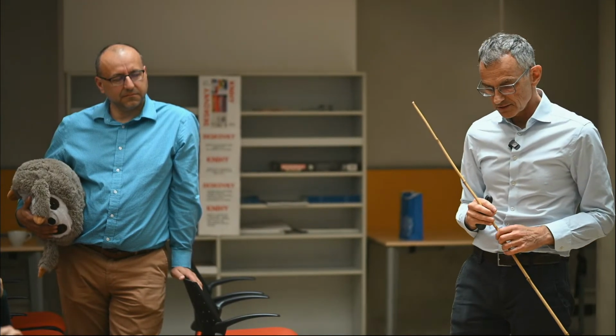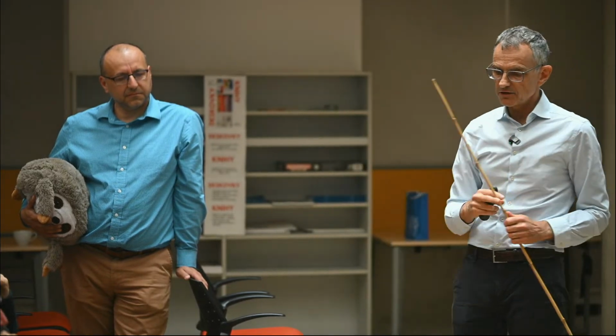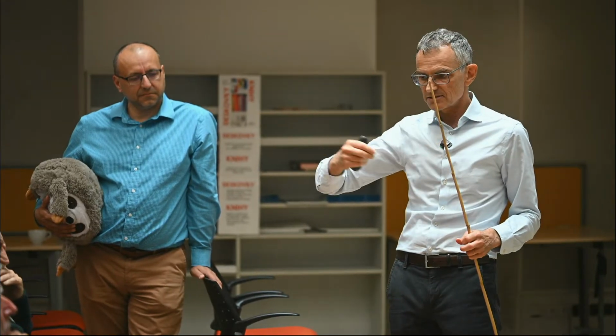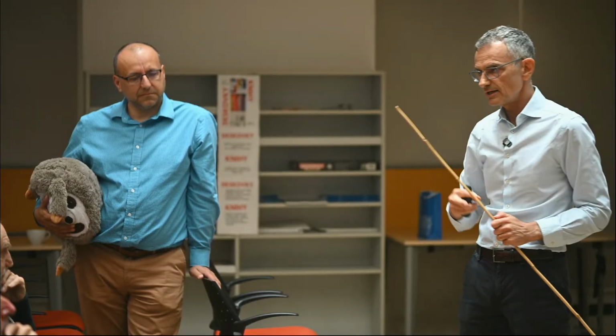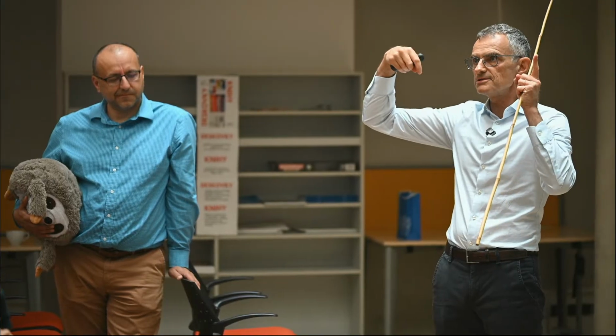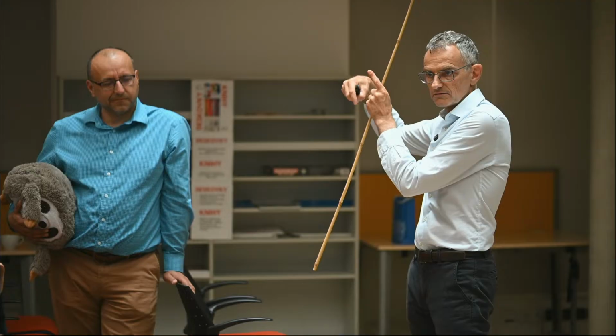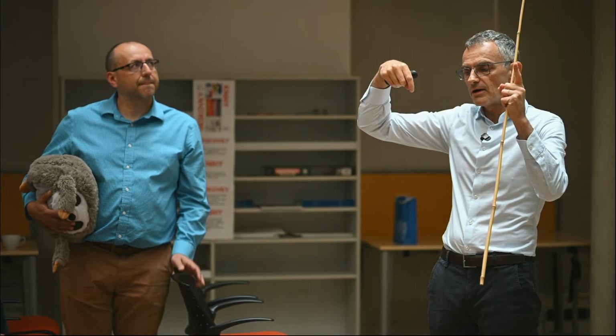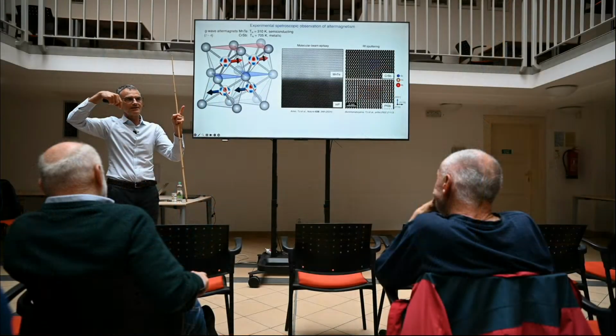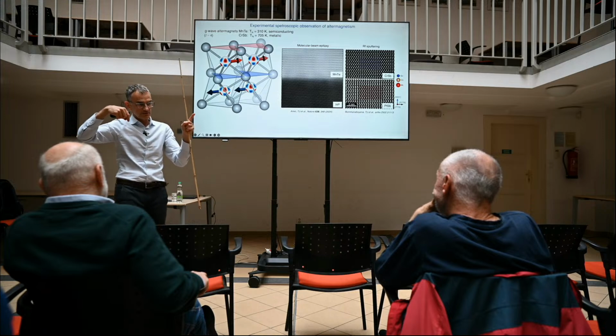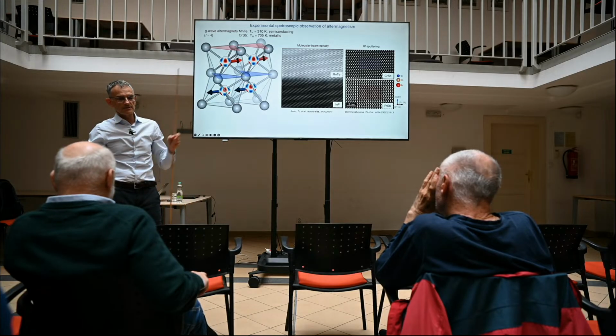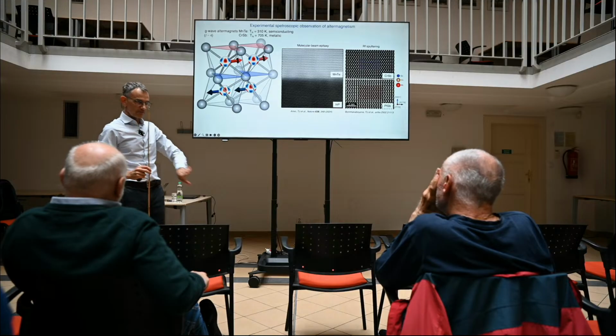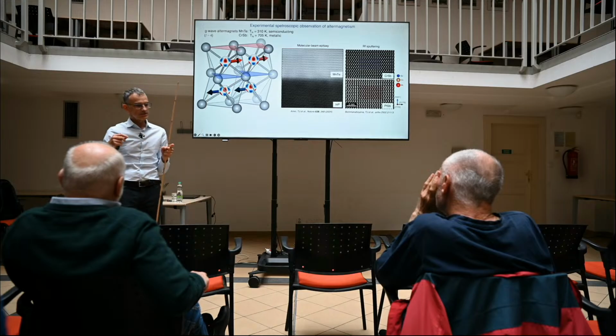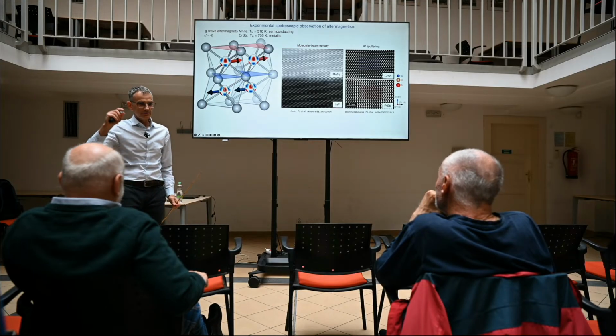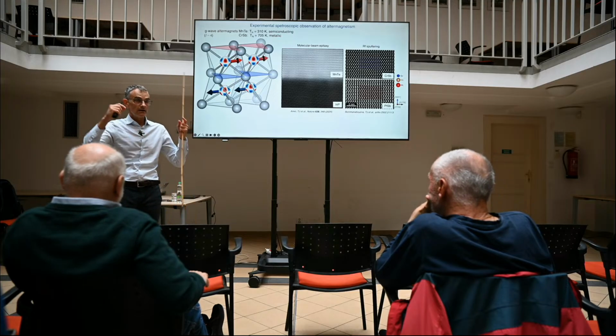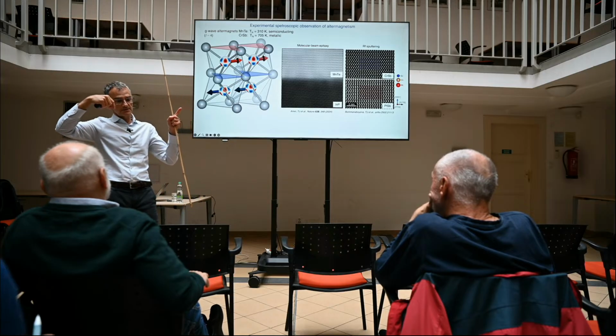Now, what is then the basic difference in symmetry? In these conventional Néel antiferromagnets, and this is also what Néel always imagined in his seminal papers and later in books and review articles, you have the opposite spins in the crystal connected by a translation symmetry transformation, okay? And what I will now say would equally apply if the opposite spins were connected by inversion in the lattice. If you had such a symmetry, then this symmetry dictates that in momentum space you will have a completely spin-degenerate electronic structure. Now, I'm not talking about relativistic spin-orbit coupling. For the translation, relativistic spin-orbit coupling in some circumstances can introduce spin splitting, but it would be the same as in a non-magnetic system. The magnetic ordering does not introduce any spin splitting if the opposite spins are related by translation or by inversion.